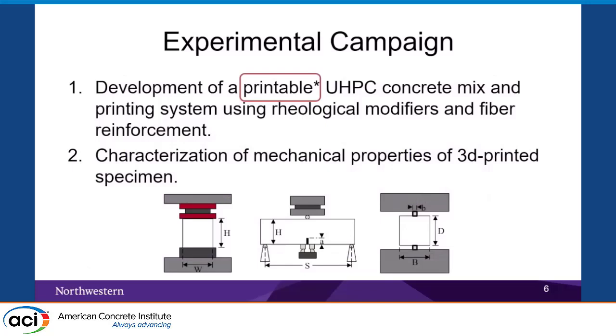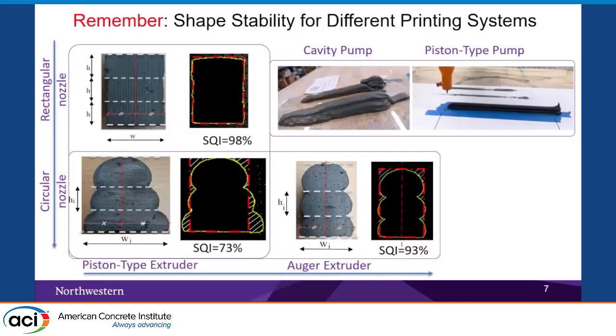In terms of the experimental program, we have two steps. The first step is to develop a nano-modified ultra-high performance concrete mix, and then we can do our mechanical characterization using uniaxial compression, split tension test, and flexure test. As you can see here, I'm boxing printable UHPC mix, based on our latest paper accepted for publication.